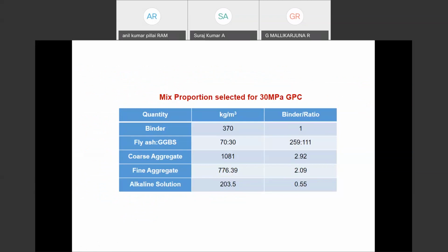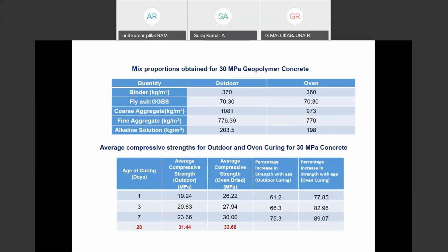For that, fly ash and GGBS, we got 70-30, and I had selected one mix to check whether this mix will get the required strength or not. So I again tested this for both outdoor and oven curing. If I go for outdoor curing, to get the required strength of 30 MPa, I had selected the binder content as 370, and if I go for oven curing, I'm going to get more strength so that I can reduce the binder content.